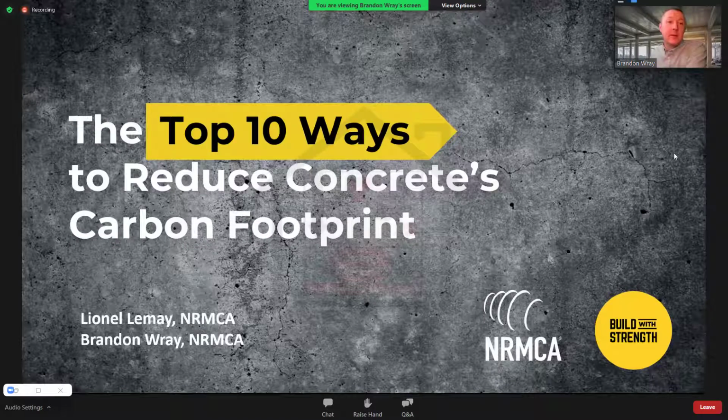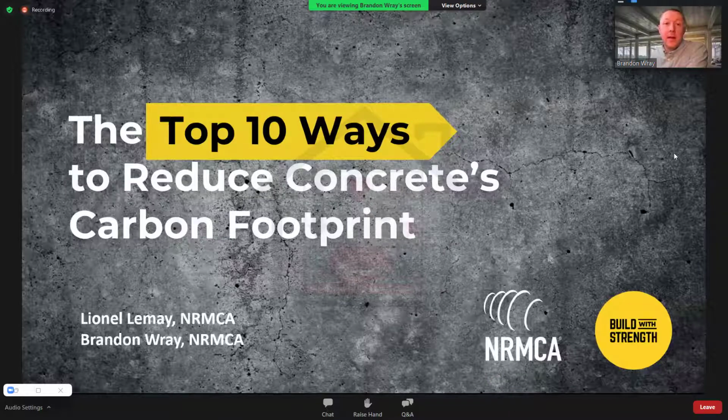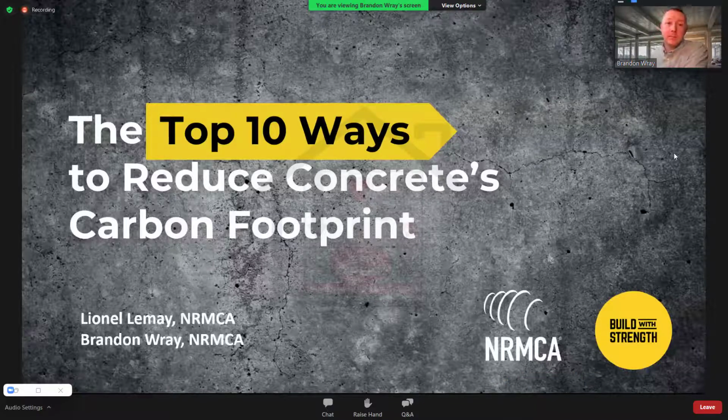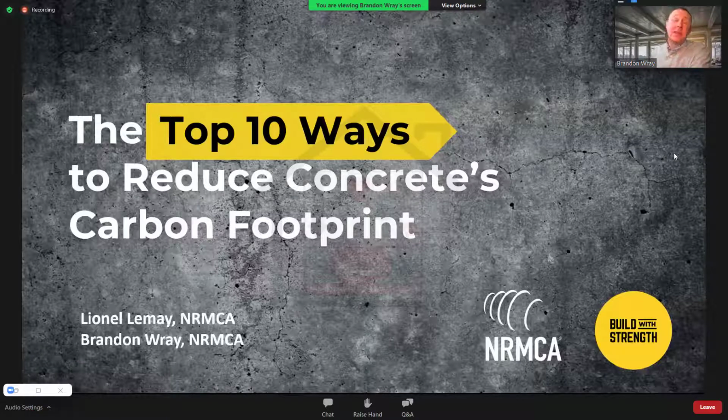admixtures to add maturity in concrete itself as it generates heat while it's hydrating as a mass material. As a whole element, it is going to realize better in situ strength than cylinders in many cases. So incorporating that as an acceptable process for 3-day strengths will allow you to work with the ready mix producer to establish a maturity curve that can then be referenced to dictate when you can stress those cables, and ultimately you'll very frequently see that the in situ material is going to have higher early strength than what is tested out in the lab.